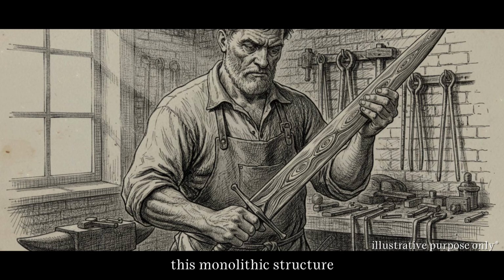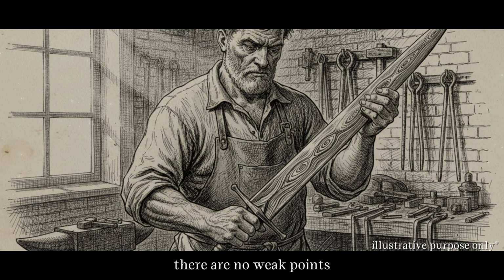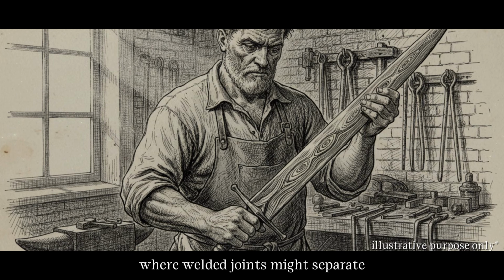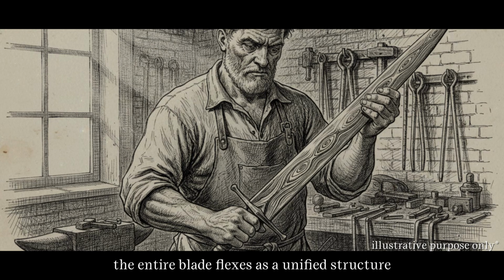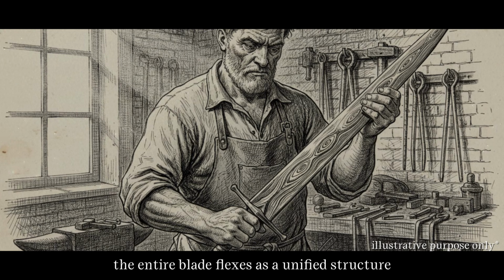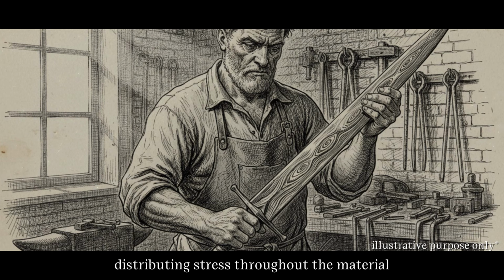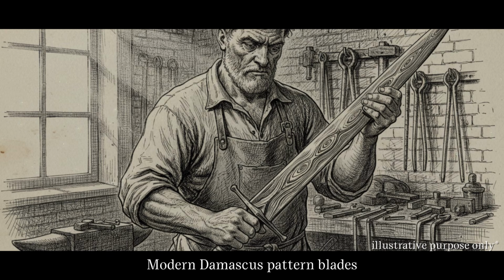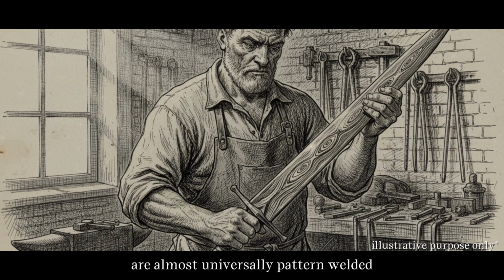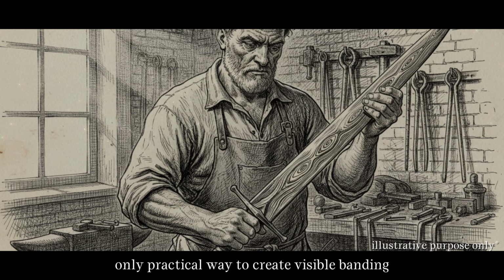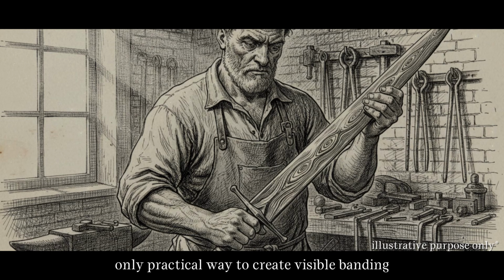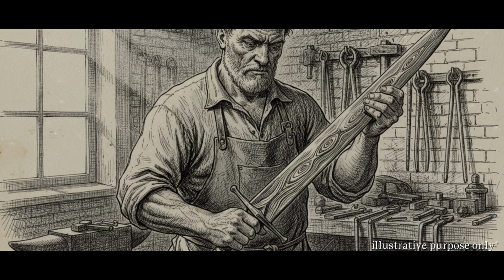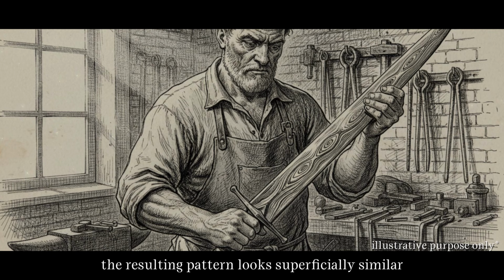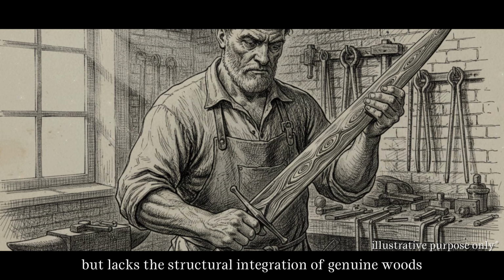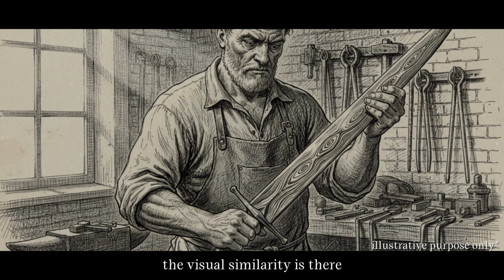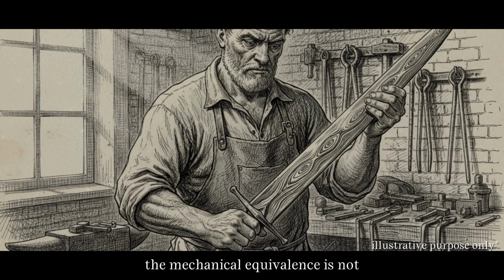This monolithic structure contributes to the blade's toughness. There are no weak points where welded joints might separate under stress. The entire blade flexes as a unified structure, with the carbide networks distributing stress throughout the material. Modern Damascus pattern blades are almost universally pattern welded because it's the only practical way to create visible banding using contemporary steels. The resulting pattern looks superficially similar, but lacks the structural integration of genuine wootz. The visual similarity is there, the mechanical equivalence is not.